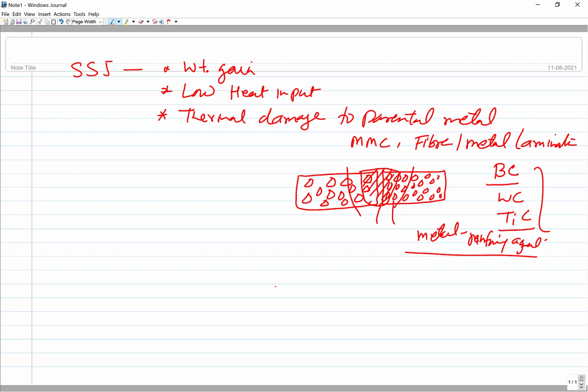And one of the most common problems related with this is the wetting and poor bonding between the reinforcing agent and the metal matrix. So this leads to a lot of pores and discontinuities in the joint. That's why, apart from thermal damage, fusion joining also promotes discontinuities in the metal matrix or fiber metal laminates or many other kinds of dispersion hardened composite materials, so they are not considered to be good. That's why solid state joining may be preferable for joining of such kinds of metal systems.